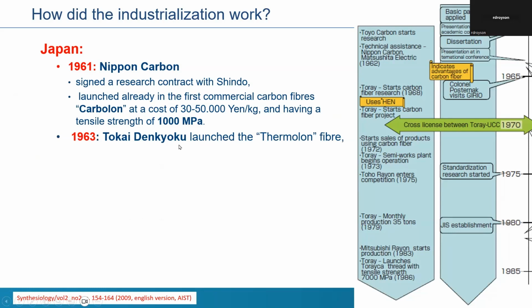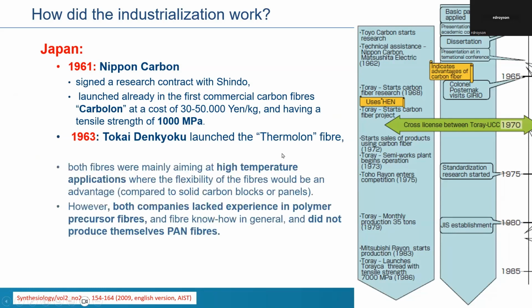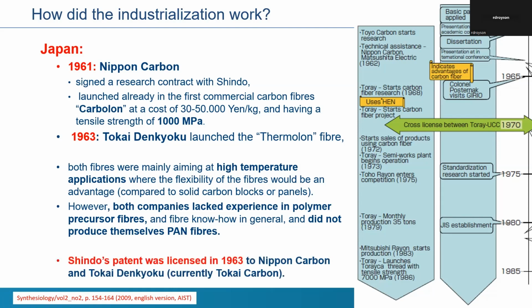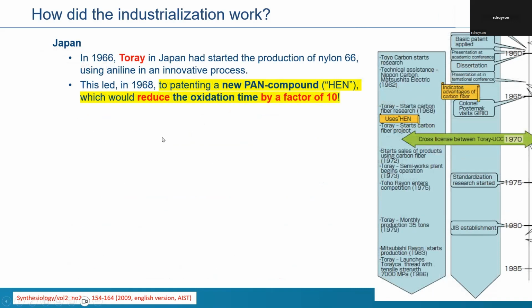Tokai Denkyoku had a similar agreement with Shindo. They commercialized the Thermolon fiber. And both fibers were not so much intended for high mechanical properties, but for high temperature applications, where the flexibility of these fibrous structures was more advantageous in comparison with solid carbon blocks or solid carbon panels. But both companies, Nippon Carbon and Tokai Denkyoku, had a problem in the sense that they lacked experience in polymer precursor fibers, and they did not produce the PAN fibers themselves. Then Shindo licensed his patent to those two companies, but the major breakthrough was coming a couple of years later.